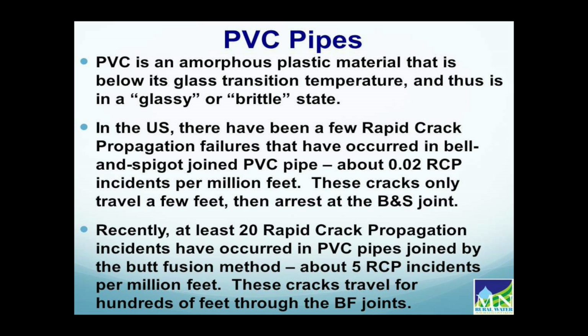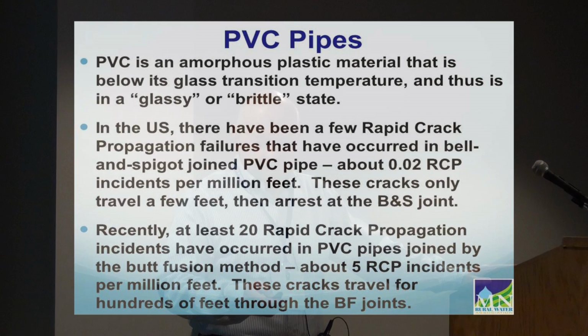Recently, at least 20 RCP failures have occurred in PVC pipe when it's joined by the butt fusion method. Now, the butt fusion method is a very good joining method, but an RCP crack will travel through a butt fusion. That failure rate is about 5 RCP events per 1,000,000 feet, and these cracks travel for hundreds, over 1,000 feet through the butt fusion joints, as you'll see.